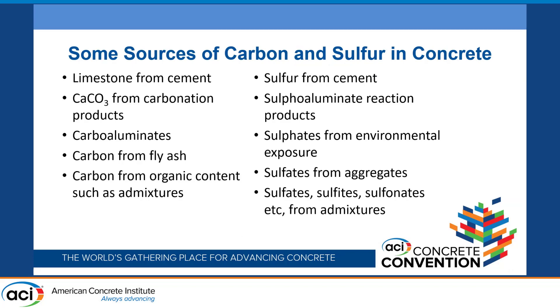Where is this carbon coming from? When you're making cements today, you'll often have high abundance of limestone in your cement. You can have calcium carbonate deliberately put there through CO2 utilization approaches, carboaluminate phases, carbon from fly ash, and even carbon coming from your additives — if your technique detects fractions of ppm, it may pick up carbon from organic materials in admixtures. The sulfur, on the other hand, could be part of an anhydrous cement phase, present as a sulfo-aluminate, come from a durability question — sulfates from the environment — sulfates in your aggregates, or additives containing sulfur.